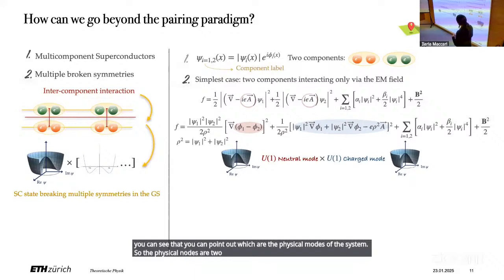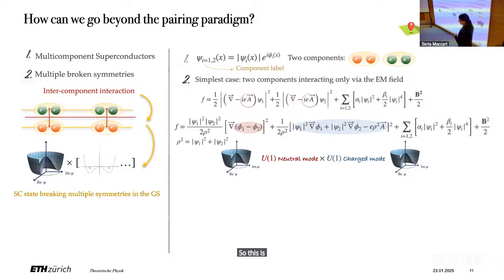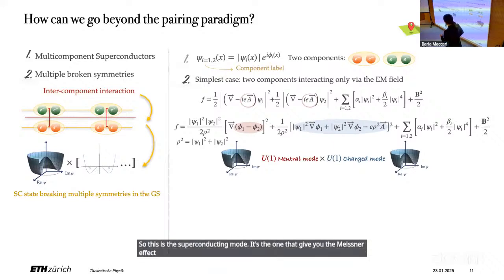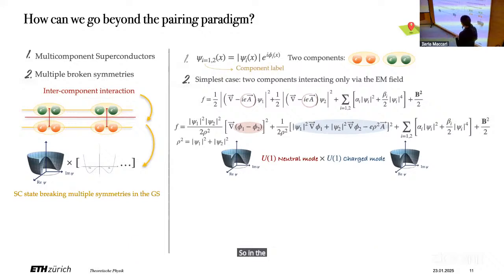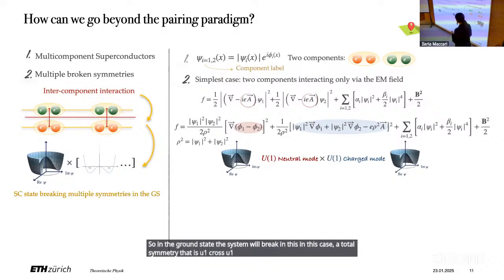There is a mode that is coupled to the electromagnetic field. So this is the superconducting mode. It's the one that gives you the Meissner effect once the phase becomes rigid. And a mode that is instead related to the phase difference, so to a counterflow of the two species of Cooper pairs, which is a superfluid mode. So in the ground state, the system will break, in this case, a total symmetry that is U(1) cross U(1). So this very simple example already fulfills the second condition.